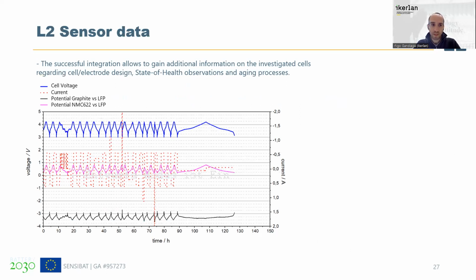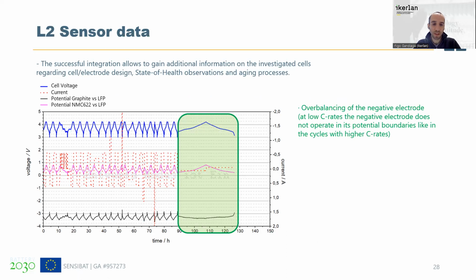And what can we do with this kind of third electrode? For example, we detected that we have an overbalancing of the negative electrode that we can see here at, I think it was, C divided by 10 C rate. So at very small charging and discharging rate, we can see that the negative electrode does not operate on the boundaries like it does at, for example, 1C here or here.